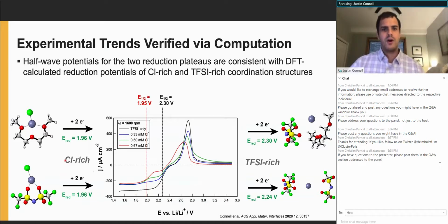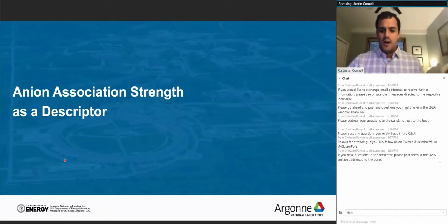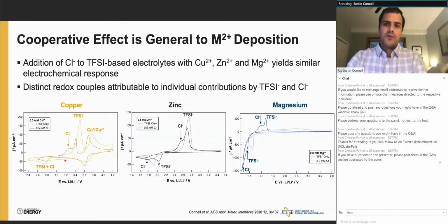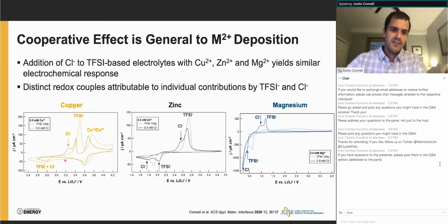So while this cooperative effect is exciting, the next question obviously is how far does this effect extend? Can we bring this to other systems? And of course, there's a magnesium ion conference, so of course I have to talk about magnesium. And so we wanted to see, first, does this effect extend to other working cations? And what we see is that indeed, if we add chloride to a TFSI-based electrolyte, we see more or less identical behavior for copper, zinc, and magnesium.